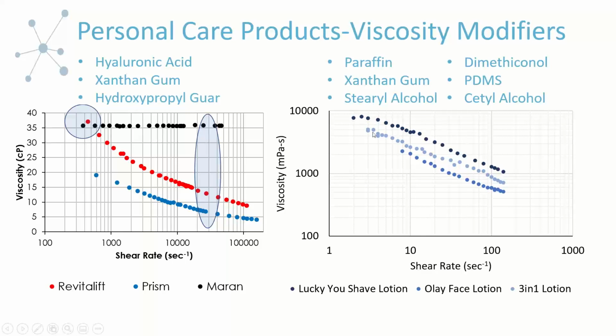And so over here on this chart, we have 3 different face lotions: shave lotion, Olay face lotion, and 3-in-1 generic lotion. We can see they have very consistent behavior. They're all shear thinning, and that makes sense given the xanthan gum, the stearyl alcohol, the PDMS, and all sorts of the other rheological modifiers that are in the system. And so all of these formulations behave similarly, but they all have different viscosities and different behavior. And so the shave lotion is generally higher in viscosity than the face lotion and the 3-in-1 generic lotion. So kind of like an in-between the two with different applications in mind.